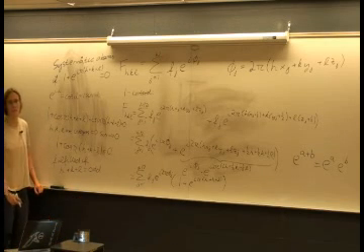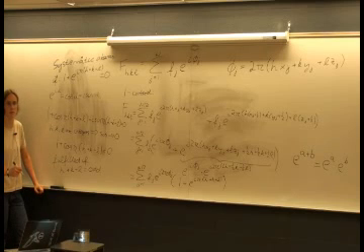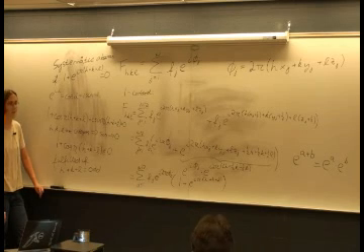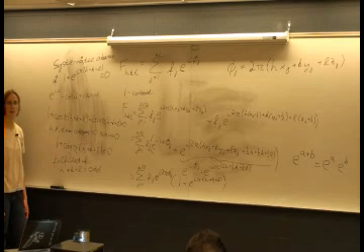So if h plus k plus l give us an odd number, then this equation is true. Because then we have cosine of pi, of 3 pi, of 5 pi, of minus 7 pi. Doesn't matter. Cosine of an odd number times pi is minus 1. In which case this holds true. So f will be 0. And we have a systematic absence.